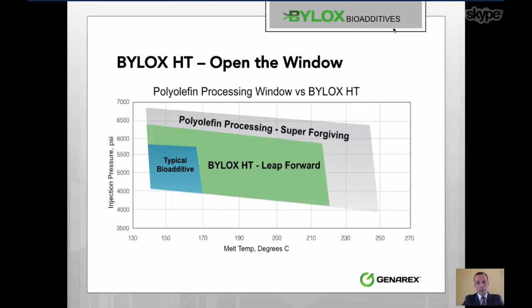We found that our product can process, this chart here is actually 2 months old. We are well past the window that we even showcase here, and we can process through some of the higher temperatures that polyolefins are processed at. I would speculate that there probably aren't any temperatures that we can't participate in. Our product is also significantly less shear sensitive than the other products in the space, and we do so at a very low cost position that allows us to bring real value without changing the price point of the finished polyolefin solutions.